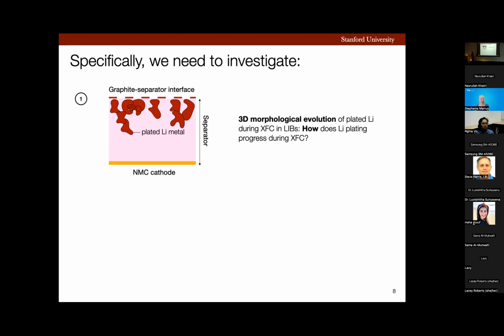Particularly, my thesis focused on investigating 3D morphological evolution of plated lithium during fast charging. Now, why is understanding the morphology of lithium plating so important, and especially in 3D? If you look at the schematic, you can see that plated lithium is hypothesized to start or initiate at this graphite separator interface, and then it forms these structures that grow through the separator, leading to battery short circuit at some point. Now, understanding morphology is important because it can give us information about the shape and size of these structures to understand how they grow.